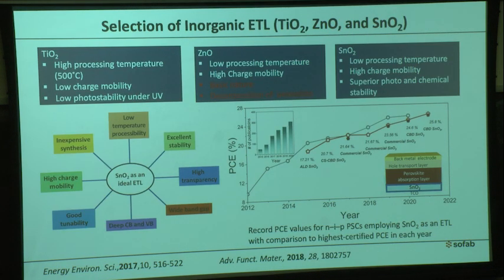Inorganic electron transport materials have several benefits: they are scalable, more stable, and inexpensive. However, not all inorganic electron transport layer materials are equally ideal. People started using titanium dioxide during the development of perovskite solar cells. It was borrowed from dye-sensitized solar cells, but it has some problems and needs high temperature processing. That's why the use of titanium dioxide is very limited, and we cannot use it for flexible substrates.